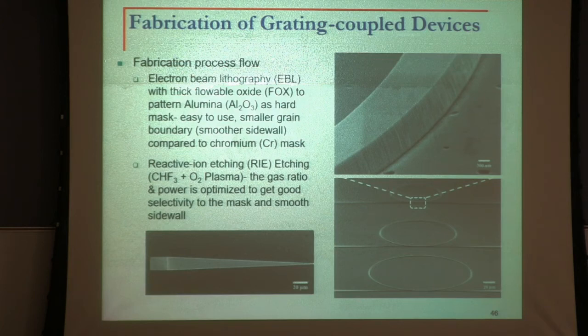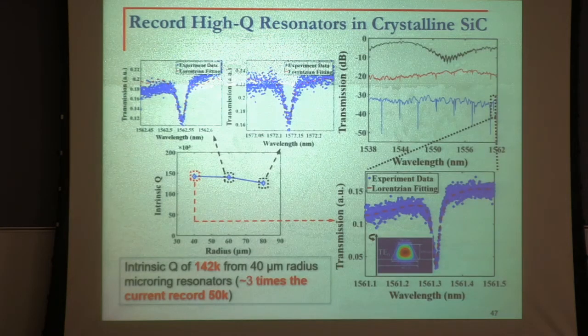We also developed an electron beam lithography and etching process to fabricate the structures. Okay. The material is not perfect. You see these voids in here. But even through that, we were able to fabricate resonators in it. So these are an array of figures that I try to explain. These are a couple of different resonators with different sizes and different resonances. The key figure here is this one that shows our observation of quality factor as a function of the radius. For this, we achieved a quality factor of 142,000, which was 3 times the existing world record. Now, the unpublished result that we have got by making this structure better is now in the 250,000 regime.